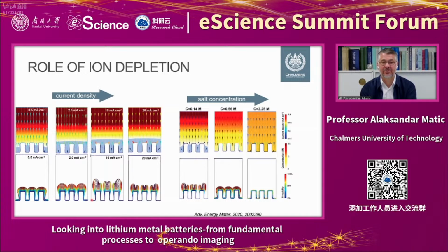The image here below is how the morphology of deposition would look on a surface. The surface consists of micrometer-sized protrusions. Where you have a protrusion, you enhance the deposition, which means that in the end you form a very heterogeneous structure. Similarly, we could look at what happens with temperature, or in the case of salt concentration in the electrolyte, where a highly concentrated electrolyte was proven to be very beneficial for forming a smooth lithium layer.